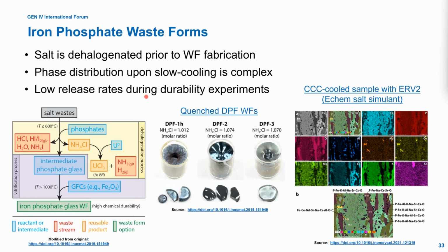The iron phosphate process is summarized in this graphic where we take salt wastes and react them with phosphates. In this case, we're talking about ammonium dihydrogen phosphate. The product from this yields an ammonium chloride that can be reacted with uranium metal to create uranium chloride, if so desired, to return to the electrorefiner or to your molten salt reactor. The other products that can form are things like acids, like hydrogen chloride, hydrogen iodide. Iodine gas is a possible product depending on how this is run. You can get ammonium iodide, and of course water is a byproduct. Byproducts from this reaction include ammonia and hydrogen.